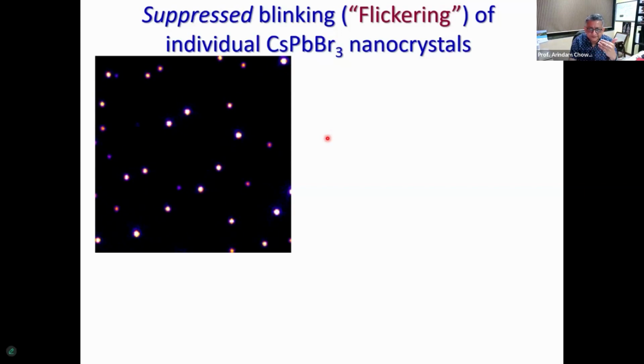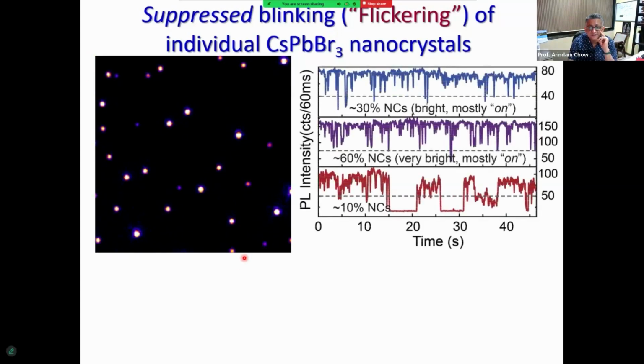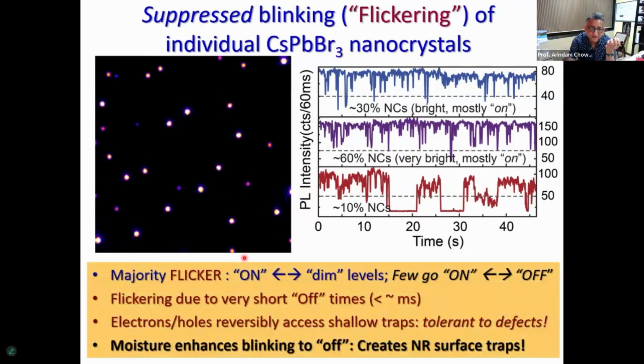But once we start illuminating them, and this is actually a movie for those who cannot see, what I have shown here on the left is a movie, and you can see that very few times you actually see blinks. It's almost like they have stopped blinking. In fact, 85 to 90% of the nanocrystals show this suppressed blinking behavior. So again, I'll call this flickering.